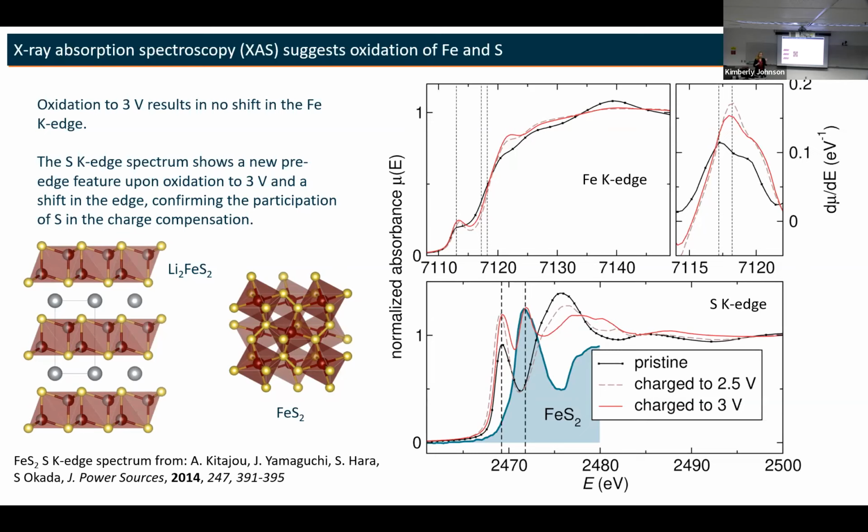So they're S2 sulfur bonds in pyrite. If we look at the pyrite X-ray absorption spectrum, we see a massive pre-edge feature here that overlays almost perfectly with what we measure in our oxidized material. And so we think that this is really good evidence that we're actually getting sulfur-sulfur bonds in this material. Whether or not we're getting octahedral iron, I'll get back to in just a minute.